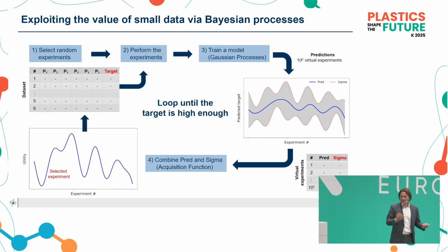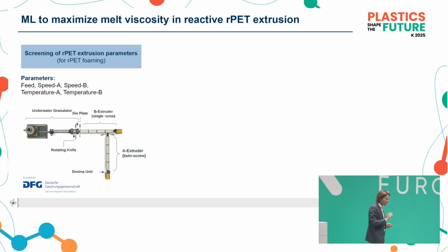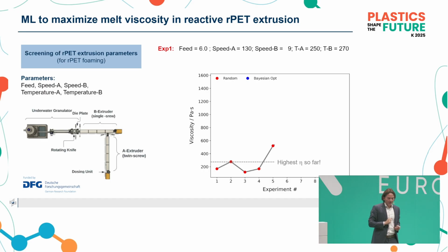Okay? So that's what you do also by intuition. If you're standing in a lab, you're doing experiments, you learn from the experiments, you think what could happen next, and then you do the next experiment. And this one is machine learning driven. An example here, and again, it's about rPET, reactive extrusion. We are doing that on a tandem line, so combining two extruders, a lot of different parameters, about 60 to 70 processing and material parameters. And that's what we've been doing.